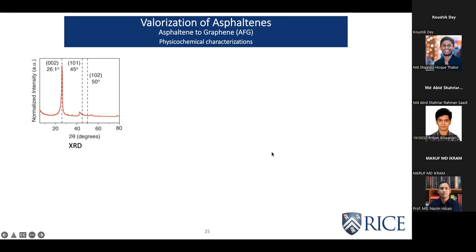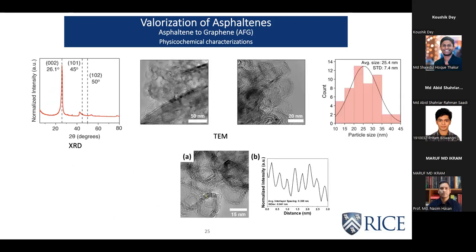We did XRD for getting the information about the crystallographic planes and their orientations. We saw the peak at around 26.1 degrees, which is typically found in graphene. We also looked at transmission electron microscopy, TEM. TEM imaging showed some of the flakes, and from the images we got the average lateral sizes of these graphene flakes, which was found to be around 25 to 30 nanometers.